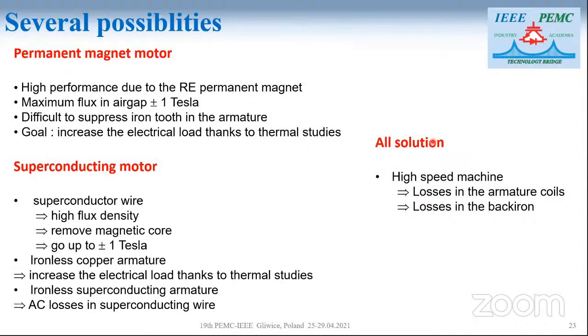And at this time, the main studies for superconducting motors and generators are made generally at low speed. So even if you use full superconducting motors and superconducting tape for the armature, you have a very low frequency and so low losses. And at this time, there is a lot of research about the reduction of AC losses in superconducting tape. For example, you can reduce the size of the superconducting tape to make something which looks like litz wire.